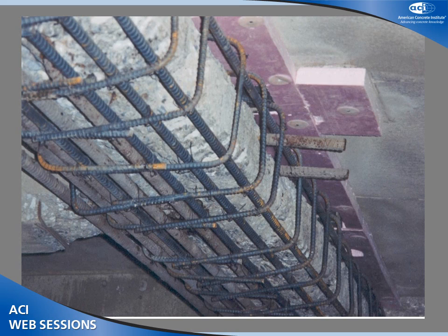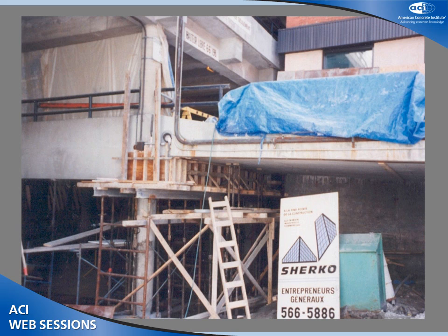But you see over here very congested reinforcement, not so much the congestion, but the cover over the rebars. On the other side of the rebars there is very, very little. And then you have a surface that is not wet enough, so retention of fluidity is very important, flowability is very important. The formwork has to be very grout tight, and it was made grout tight and was tested with water, like Chelik was telling us.